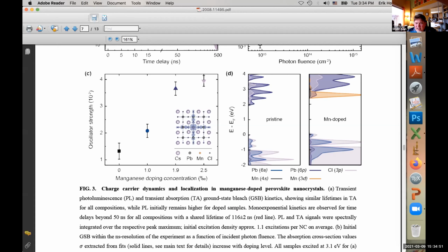So it creates a qualitative confusion. In the paper with Aaron a couple of years ago, we were considering photoluminescence of manganese-doped perovskite. It was really low, orders of magnitude lower than one would expect in reality. And my understanding is that it is primarily due to the qualitatively wrong alignment of levels.